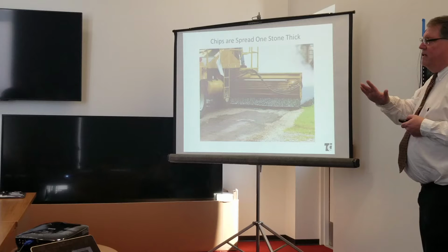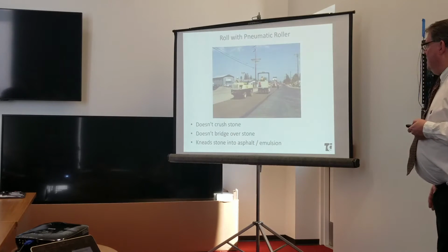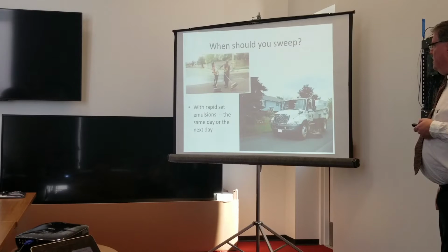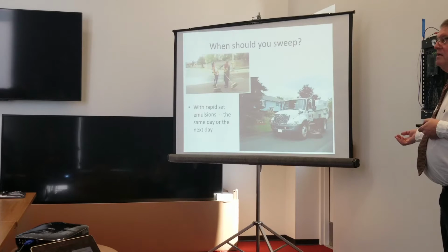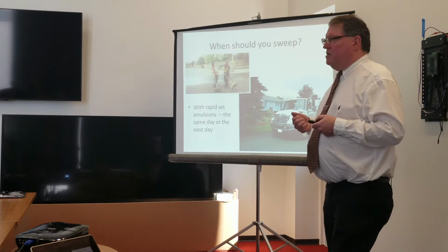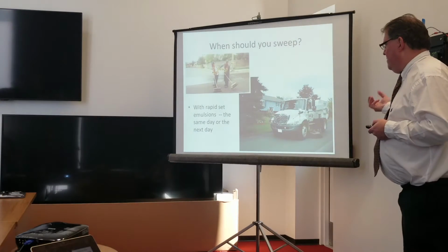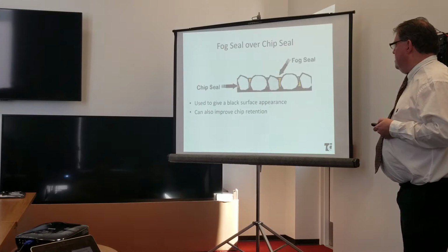On the other side, if you pay by the square yard, you have to make sure you get the minimum amount you specify. Roll with a pneumatic roller. If you're using rapid set emulsions, same day or next morning sweeping. Chips are not magically going to embed themselves into the asphalt a week later. It's just not going to happen. Once that asphalt has set up, those extra chips aren't helping you out.